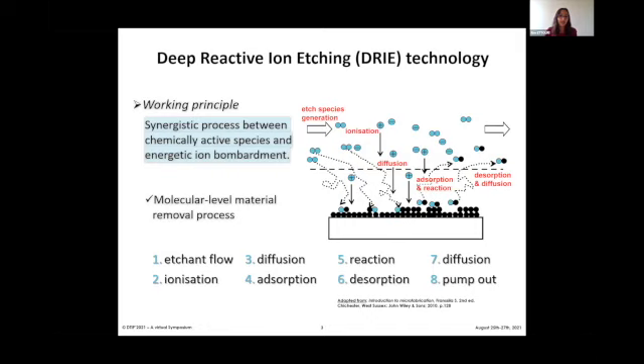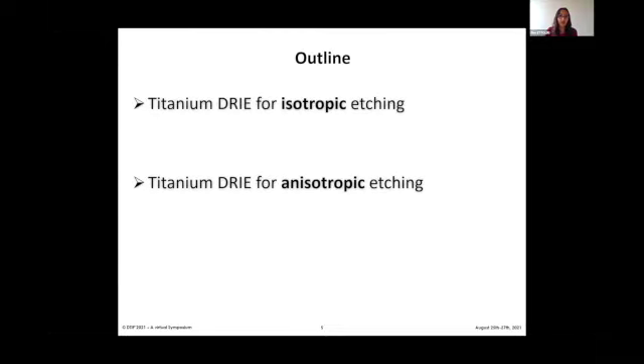We can say that plasma etching can be divided into two main types of interactions. The first one is the generation of chemical species, and the second one is the interaction with the surrounding surfaces. The reactive species diffuse to the surface of the substrate where they are adsorbed. The adsorbed species then react with the surface, resulting in the formation of volatile reaction byproducts that diffuse, removing material or layers from the substrate.